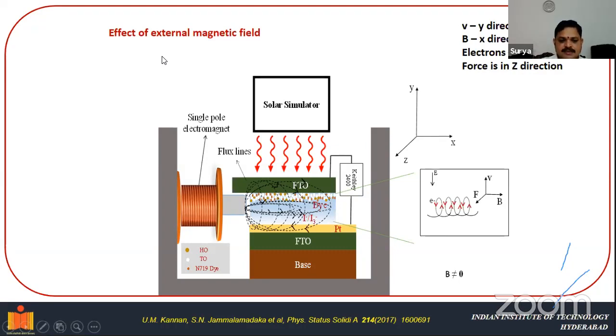As I mentioned previously, there are various ways by which you can improve the efficiencies. One is absorbing more light from the sunlight, which we achieve using the dye. As the dye has a broad spectrum, it can absorb more and more light. That is the first thing. The second thing is spin orbit coupling. We have already seen that because of the spin orbit coupling, the transition between the singlet excited state and the triplet excited state is unlocked. As a result, the recombination time is enhanced. We would further like to enhance it by applying a magnetic field externally to the device.